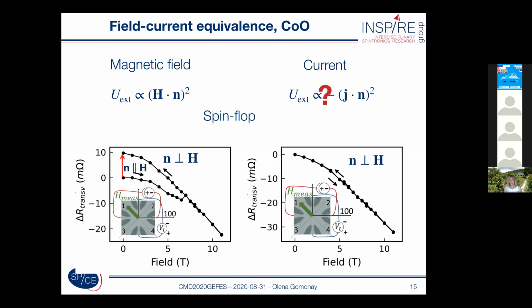So if we start with a parallel orientation, then at the field around 6 Tesla, the system flips perpendicularly. But when we remove the magnetic field, the Néel vector stays perpendicular to the magnetic field, because it's also an equilibrium state of the system. However, if we start initially from the configuration when the Néel vector is perpendicular to the magnetic field, then nothing changes when we switch the field up and down, because the Néel vector is always happy in this configuration, as can be seen from the right lower panel of this slide.